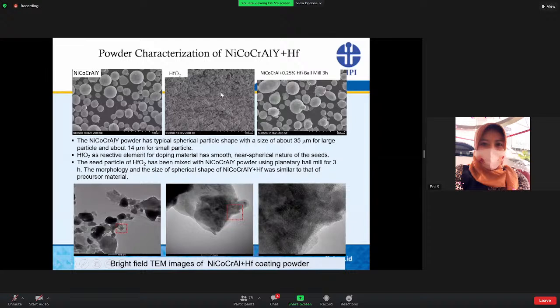Hafnium dioxide as a reactive element for doping materials has a smooth, near spherical nature of the seed, as shown in these figures. The seed particle of hafnium has been mixed with the precursor materials using a planetary ball mill for 3 hours. The morphology and the size of the spherical precursor material were similar to those without additions of reactive element. Therefore, the structure of hafnium as a doping element is hard to observe using SEM.